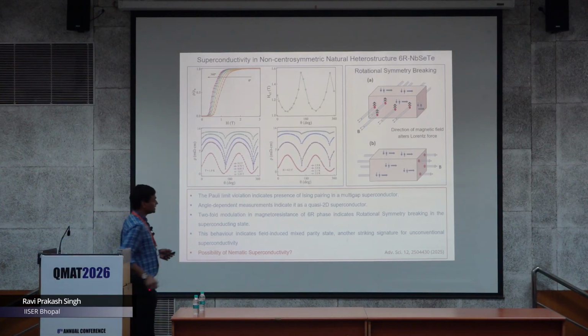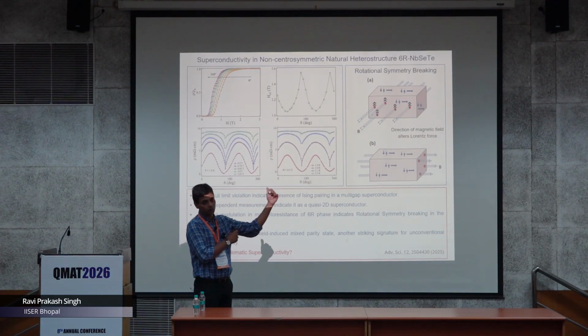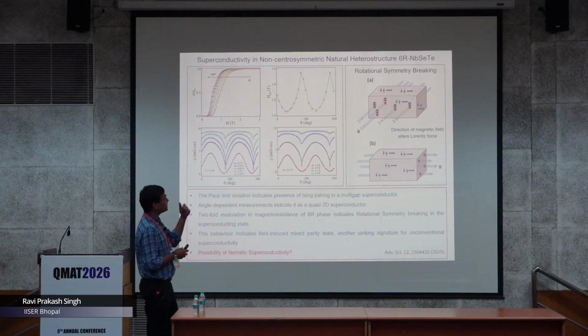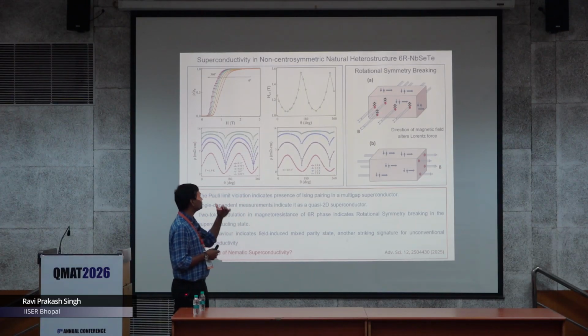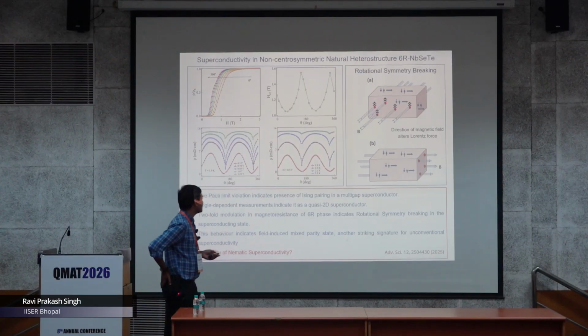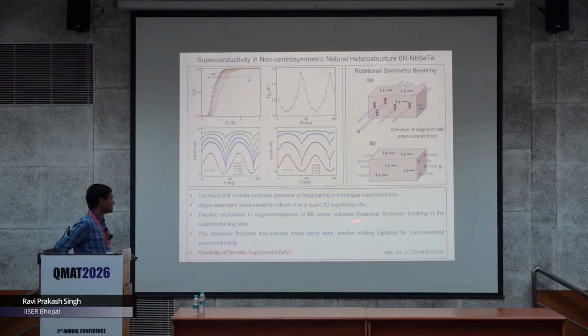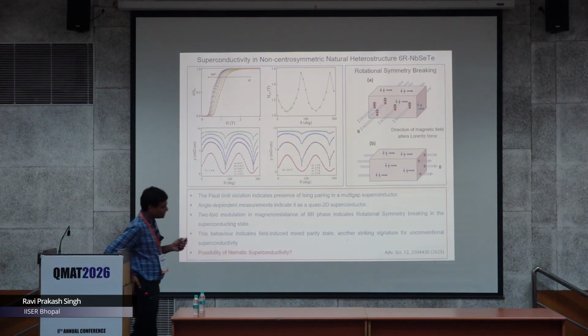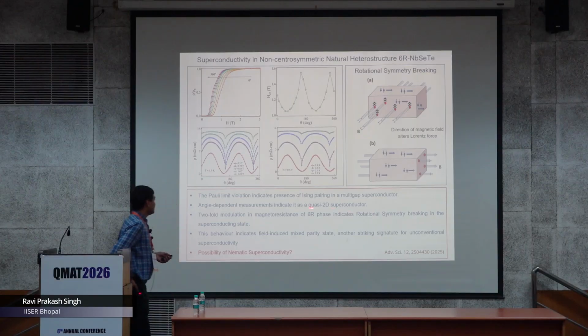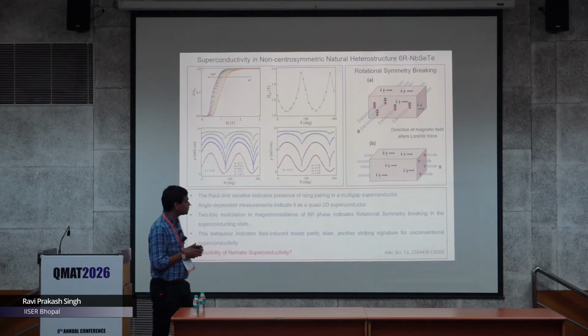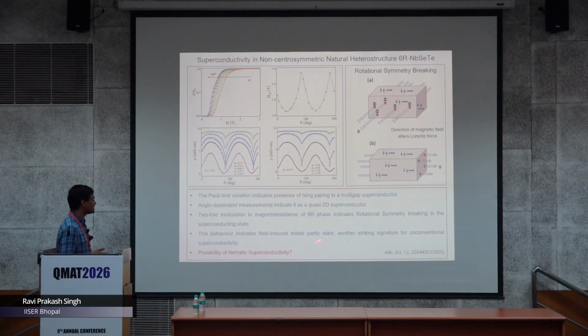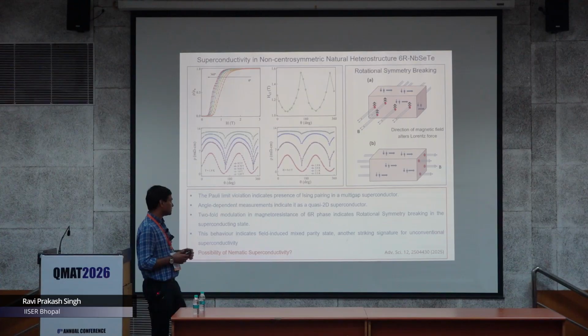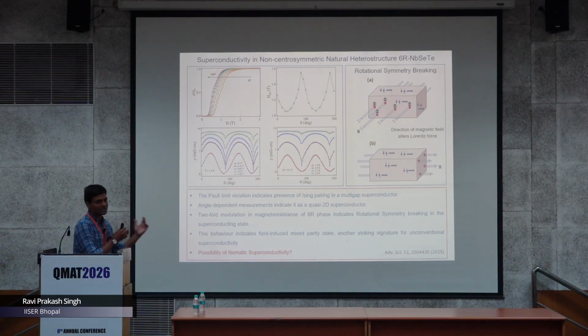Hc2, and it is suggesting that, because it is 6R, we should expect sixfold, but we are getting only twofold. Sometimes you can get threefold in 6R also, but here we are getting twofold. So it looks like twofold modulation in magnetoresistance indicates rotational symmetry breaking in the superconducting state. And because it is twofold, it is not possible with only an S wave. So it looks like the superconducting ground state is mixed. Maybe it is SP or something like a mix.